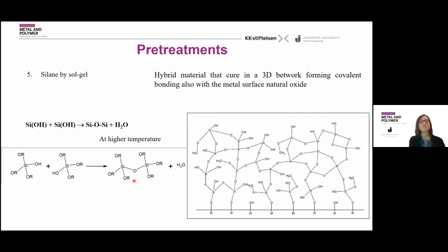This reaction, if done in contact with the metal, can also happen with the first oxide layer of the metal. And therefore, if you do a pre-treatment based on silane, you don't only oxidize the surface into a known chemistry, but you are actually creating a covalent bond that is among the strongest bonds chemically you can produce between the substrate and the pre-treatment. Moreover, you still have a lot of free bonding sites for the next level.